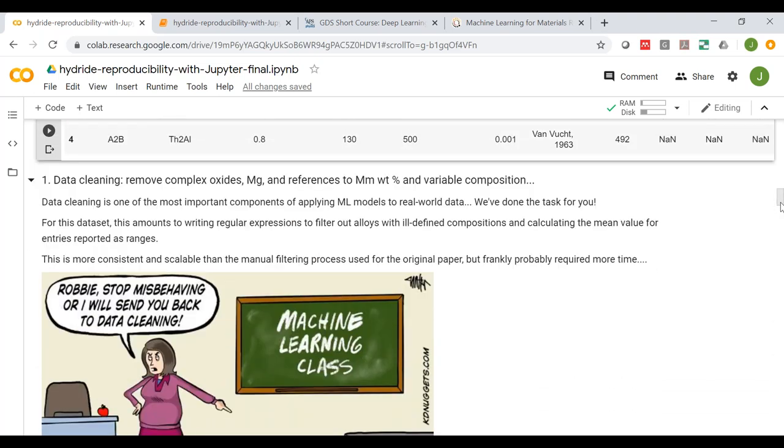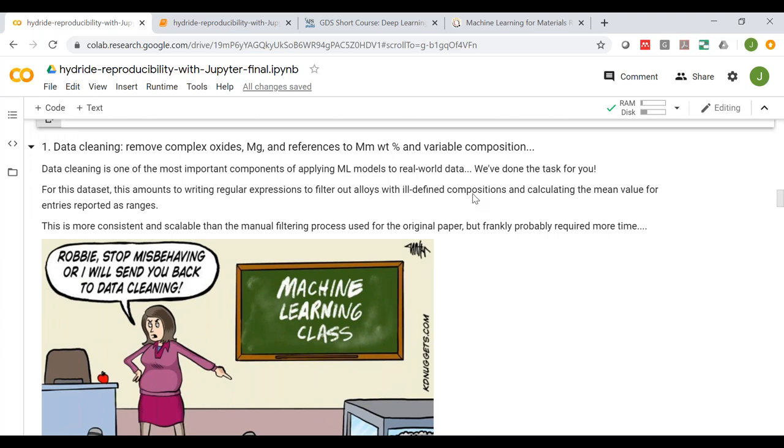And actually, we're going to have to get rid of a lot of things because the physics of hydrogen storage materials changes, whether it's bound to something like boron, as in lithium boron hydrogen, or like alane where it's directly chemically bonded to aluminum, versus an interstitial hydride, versus an adsorbent material that only adsorbs hydrogen through weak physisorption properties at very low temperatures. And so in building a model to predict new interstitial hydrides, the first thing you have to do is strip out from the data set anything that has different physics associated with it, unless you have a good descriptor or differentiator between the two, which to my mind at this point, we do not have.